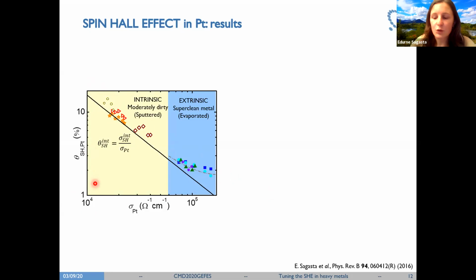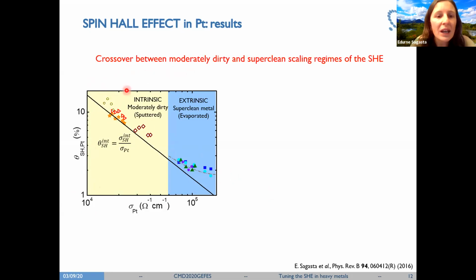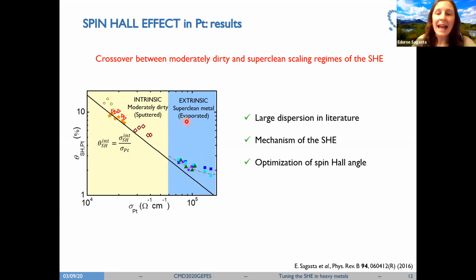So what we are seeing here for the first time is the crossover between the moderately dirty and the superclean scaling regimes in the spin Hall effect. And we are reproducing the large dispersion in the literature, because just by modifying the resistivity, we have been able to tune the spin Hall angle from 2% up to 14%. Also, we have unveiled which mechanisms are dominating the spin Hall effect. We see that in the high resistive regime the intrinsic mechanism dominates, and in the high conducting regime the extrinsic one. And also, we are showing a path that shows how to optimize the spin Hall angle, which is to increase the resistivity of the material.